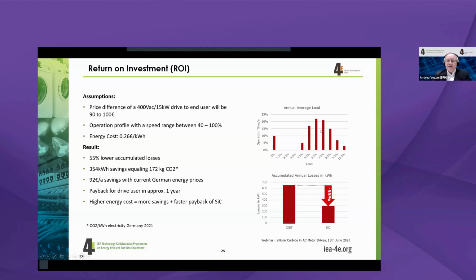And if you take this into account, you have to then look at the efficiencies at these different speeds, look at the energy which is turned over at these speeds, and look at the savings you have, multiplied with the electricity cost in Germany in 2021, which is 0.26 euro. You would have then total annual accumulated losses, and you have this for silicon and silicon carbide, and you have a reduction of roughly 55%.